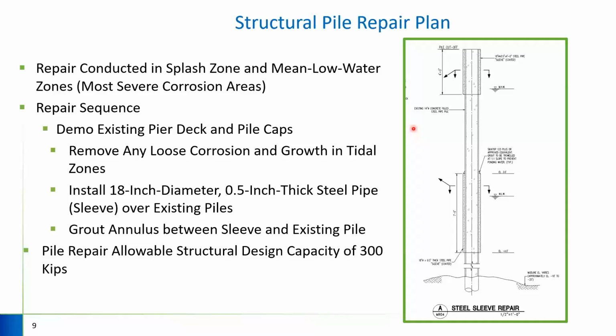And the repair itself consisted of demoing the existing pier deck and pile caps, and removal of the loose corrosion and growth in these tidal zones, which consisted of air blasting above the water level and water and sand blasting below the water level. Upon completion of the cleanup of the pile itself and removal of that loose corrosion, we installed 18-inch diameter, half-inch thick steel pipe sleeves over the existing piles.